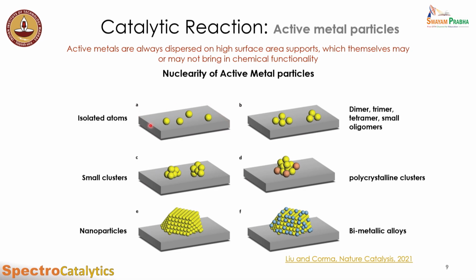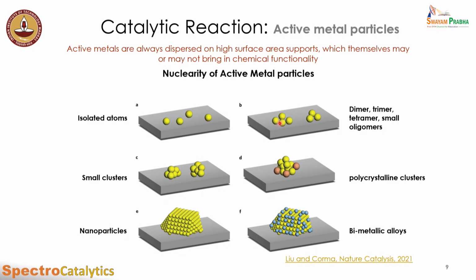We take a very high surface area support material, and then we try to deposit all these active metals on the surface, and because of the size of the active materials, we can have different surface to bulk ratios. We can have isolated sites, meaning just one atom of this active metal is present on the surface. We can have small oligomers, like a dimer, trimer, or tetramer type of species, and if you notice, these are still two-dimensional species.